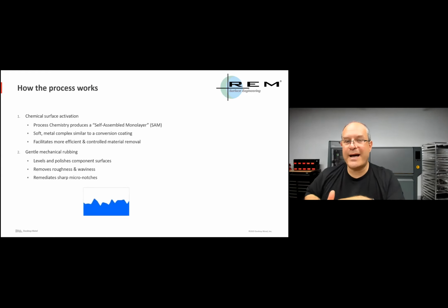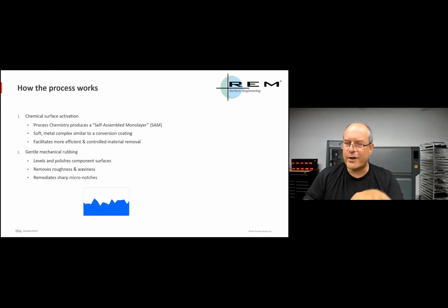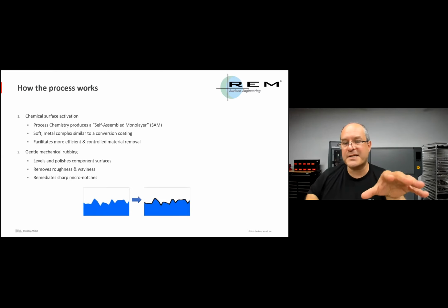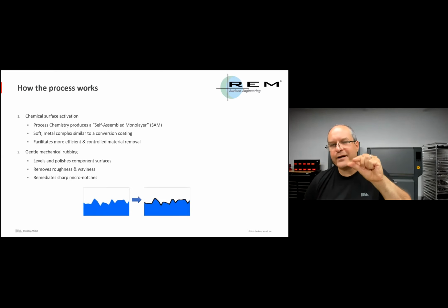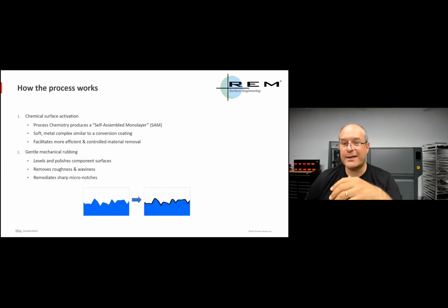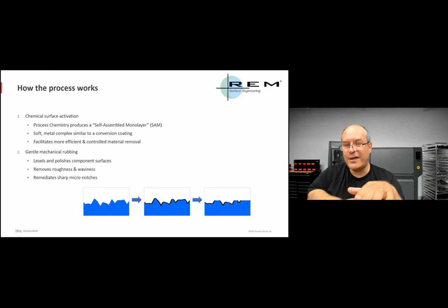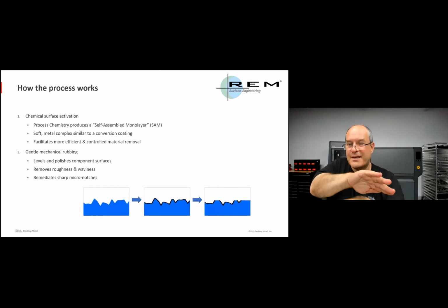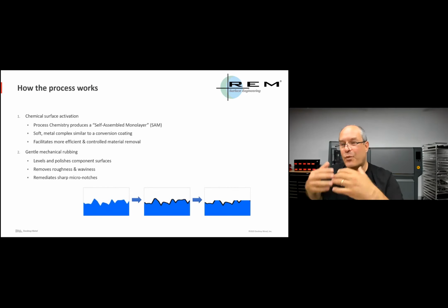So here you have a chemical surface activation where you start out with a surface that can be rough. Then there's a process chemistry that reacts with a thin layer of this surface, creating a conversion coating that's now soft, relatively brittle, and easy to remove with a lot less force than we normally would. And then there's the continuous mechanical rubbing. That mechanical rubbing removes the stuff off the very top of the surface, the peaks. So the mechanical rubbing removes the peaks, not the valleys.